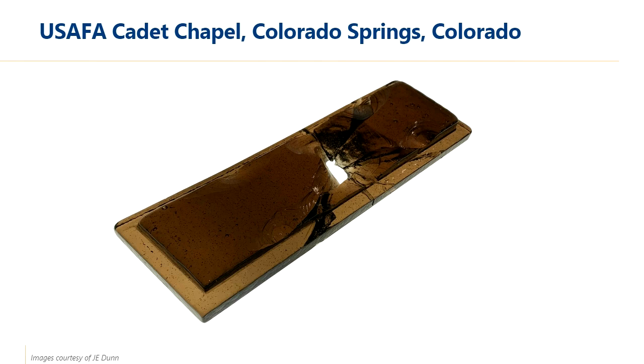It had multiple fractures and missing glass. So in this one instance, the block needed to be replaced. But doing so and replicating the color from 65 years ago posed a significant challenge, a challenge with a unique solution. The glass block would be recast by melting down the original piece.